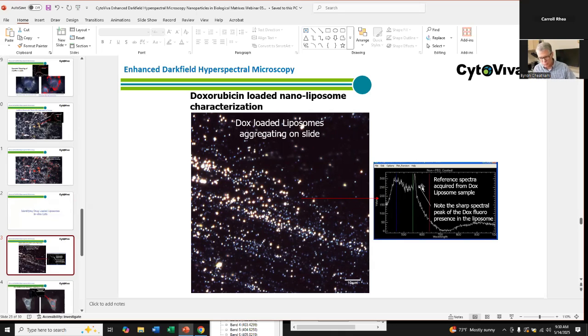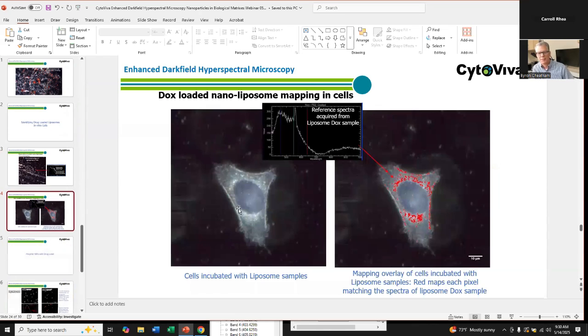This spectrum is very interesting. Doxorubicin, as many of you may know, has a natural fluorescence. It has a peak, if you measure it, somewhere around 575 nanometers. If you look at these doxorubicin-loaded lipid liposomes, you see that it has a real interesting sharp peak exactly where the doxorubicin natural fluorescence is. That's part of this overall spectrum. And that can inform us to be able to identify where these dox-loaded liposomes are in this mammalian cell culture.